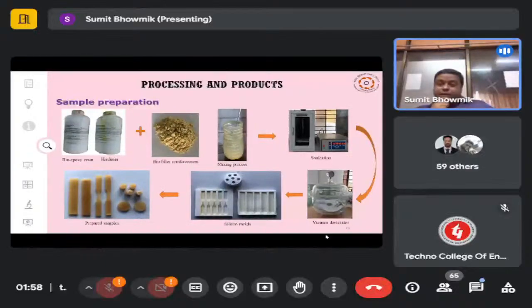Then they have to be mixed in the sonication with a specific RPM. As I mentioned, in fiber-based composite material, the main issues come with orientation and delamination, so homogeneity and isotropy. If the epoxy and the filler need to be properly distributed, then sonication with a specific RPM we have to carry out.